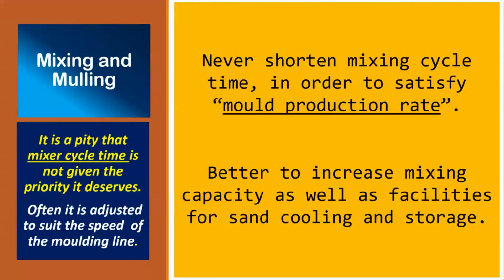So what is the best way? You always should have a buffer inside the sand system so that any change happening on the molding side can be absorbed. Sometimes you might increase the hydraulics by putting an additional pump, so you can shorten the cycle time by maybe 10 or 15 seconds, by which you will be able to produce some 10% extra molds. So all these are possibilities in the production. If you have a larger capacity for sand handling, sand mixing, and sand delivery, then you are better off than cutting short the cycle time and spoiling the sand mix.